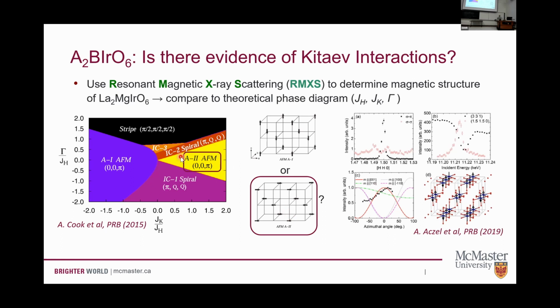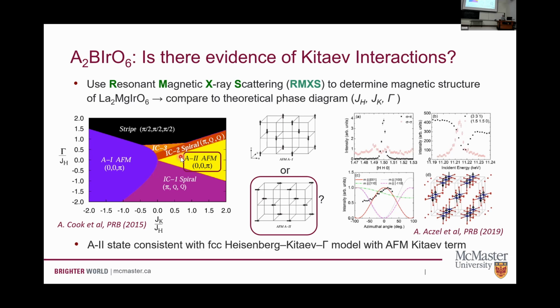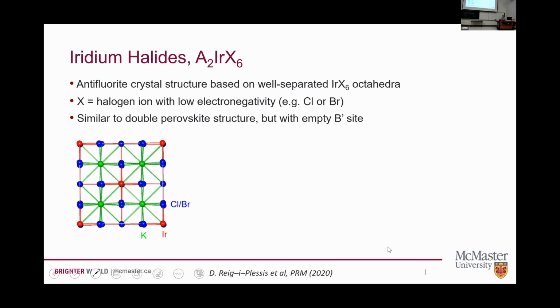Okay, so we've used spectroscopy to tell us that this J effective 1/2 picture is a good description. Now we use the elastic scattering to tell us what the magnetic structure is. And that gives us a way of, at least indirectly, attributing this to an FCC Heisenberg-Kitaev-gamma model with an antiferromagnetic Kitaev term. We could do the same kind of exercise on the iridium halides.